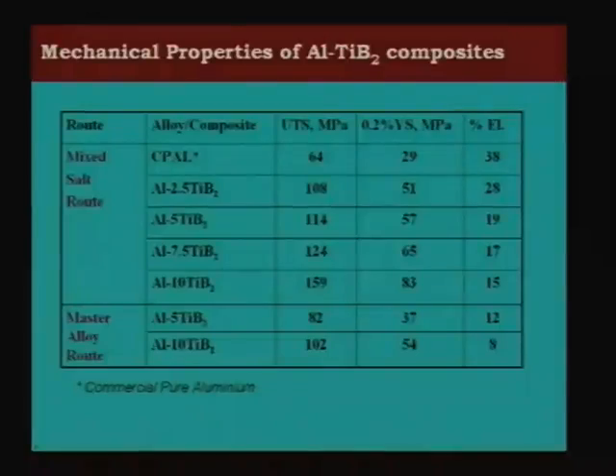So this is what you get with aluminum. If you take pure aluminum, you get a UTS of only 64 MPa. And if you add about 10% of TiB2, you can go from there to here, almost 3 times increase, or more than 2.5 times increase in the strength that one can achieve with this. And carefully see, the elongation has not really gone down, it has not really become brittle. 15% elongation is a great elongation for a composite.